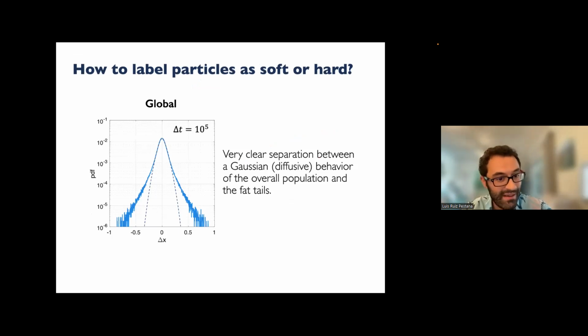So what you are seeing here is the distribution of the global non-affine displacements just in the X direction. That's why you see negative and positive, and this is symmetric, right? So why is this curve better than the other curves? Well, it's better because I can fit a Gaussian curve to the data, okay? And I can see where the tails actually deviate from the Gaussian.